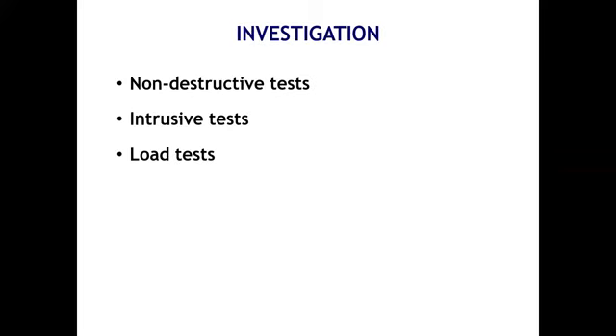Normally in India, they commonly adopt non-destructive tests as follows: rebound hammer and penetration technique, ultrasonic pulse velocity, core drilling test to evaluate the equivalent cube compressive strength of the concrete, carbonation test, half-cell potential test, evaluation of chloride and pH through concrete powder samples in terms of durability, and Profoscope survey for identifying the cover, and then the rebar which is already located.